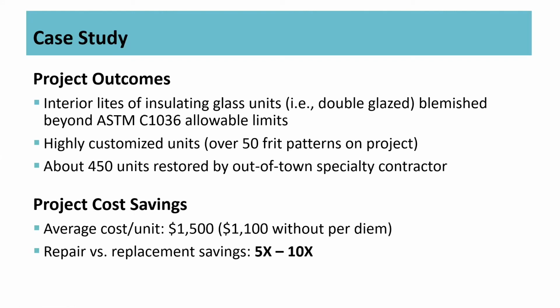Project cost savings. Well, as Mark indicated before, these really nice facades can be a liability, and they are quite expensive, especially if we start shutting down roads or getting cranes involved and trying to replace this. Certainly a significant cost at the order of 450 units. I mean, that could be the entire building or at least half of it. So in this case, we reduced the cost down to about $1,500, or without per diem, $1,100 per unit. So that's still a big number, but that's a whole lot less than replacing the entire facade. And so in this case, it was a 5 to 10 times reduction in cost. Okay, so that's a huge difference on that one.